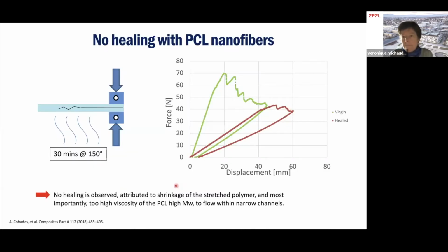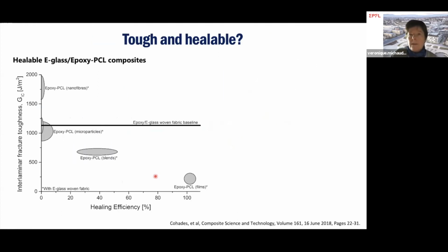Do we get healing? Well, we did the same experiments as before. We closed the crack. We let it for 30 minutes at 150 degrees. And unfortunately, no healing was observed at all. And we understood why and published this actually. It's attributed to the shrinkage of the stretched polymer, and most importantly, the PCL that we use at a high molecular weight in this case, with a very high viscosity, a very thin microstructure. So it was very difficult for it to flow within the narrow channels. So our conclusion at that time, it was a few years ago, was that if we look at making a tough and healable composite, it is a challenge.